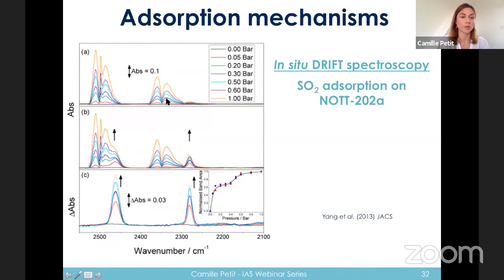And if you subtract the first spectra here, you'll get the bottom one here that gives you, in a way, increasing intensity and increasing area of those peaks related to SO2 for different pressures. And from that, you can start building an isotherm for that specific SO2 adsorption in that specific MOF.